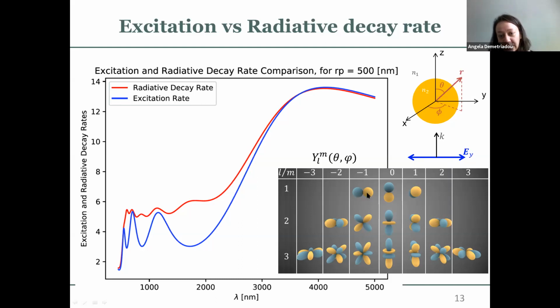And you can immediately see that, well, I'm sending this polarization, I'm going to have the plasmonic dipole resonance oscillating like this, which is basically the first order mode here. This one here, you're going to have a plus, minus, which is what this one is showing. But if I put my dipole at this position here, it means that you're going to see a 0. You will never be able to couple energy to that emitter from this particular mode. However, for the third order mode, you're going to have a maximum, and so on. It goes on like that for the higher order spherical harmonics.